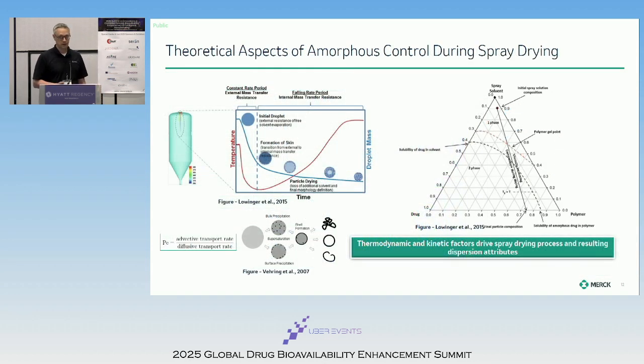Now we can pivot over to spray drying, because similarly with this technology, very complex, it's going to lock in key attributes, and we need to make sure that they're controlled as part of how we're developing our drug product and our amorphous dispersion. So in the spray drying process, essentially we atomize droplets and rapidly evaporate off the solvent. That droplet formation process is actually quite complex, happening over very rapid time scales, but you will follow a droplet drying trajectory proceeding through the phase diagram on the right that you can see. And so you go from a multi-component system to a uniform homogeneous spray-dried particle, and the rate at which you transit can lead to different attributes within your spray-dried dispersion particle.